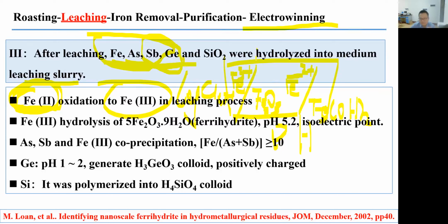So there is some difference between the precipitation of these 2 ions. And zinc is somewhere in the middle. So if we want to separate iron from zinc, the good idea is to oxidize this ferrous iron into ferric iron, which will precipitate when zinc ion is stable.